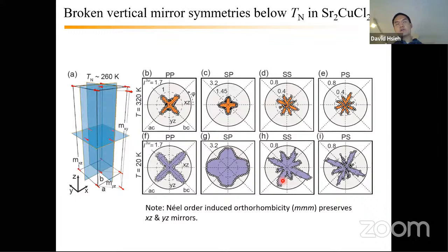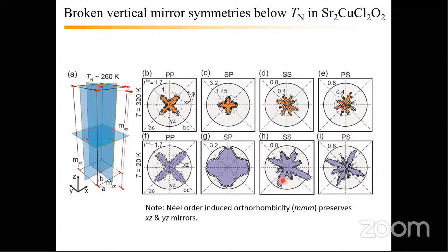How sensitive would we be if in principle there is some tilt? Go ahead. I wouldn't worry for the bulk response, but if we grow thin films, we grow them on realistic substrates, and they are polished with some error. I think half a degree is not uncommon, and the best you can get is, let's say, 0.1 degree off. So it means that the film is also tilted a little. The copper oxygen planes are not strictly parallel to the surface. They are tilted by, let's say, half a degree. If you're probing the bulk, that may not be an issue, but the surface response will have C4 symmetry broken by this tilt.